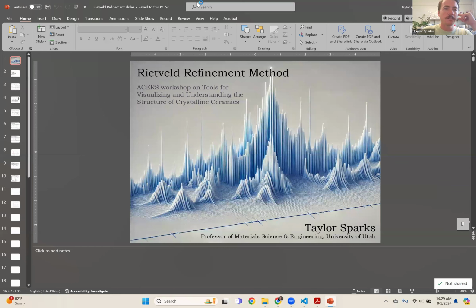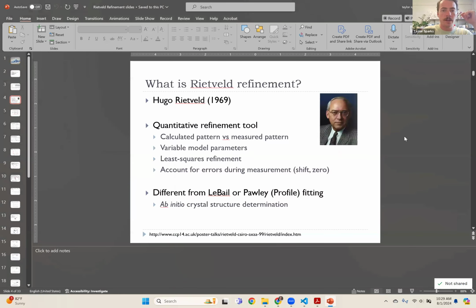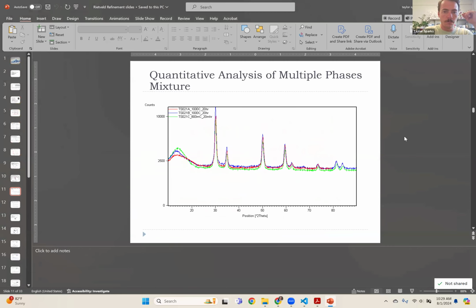Let me briefly come back to this. So if we jump ahead in our slides, when we talked about right there. If you see a big amorphous bump like this, you have two options. First off, you can just try and, well, I guess you have three options. You can try and fit that amorphous bump with a more complicated background function. For example, we're using the Chebyshev polynomial with just three terms. You could crank up the terms and just try and fit it, right? That's one option. Second option is just cut that part off.